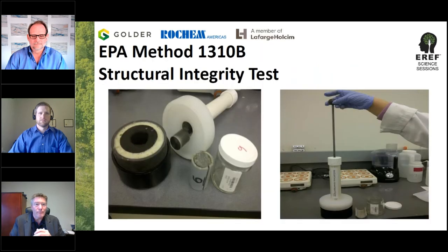And the method that I like the best, and I think the one that is the absolute most relevant, is EPA method 1310B. It's called the structural integrity test. You make these little monoliths. If you'll see in the left picture, there's a number 6, and there's a mold of a prescribed size, 7.1 centimeters tall, 3.3 centimeters across. You make your mix. That's that little vial that you see there, or that mold, that used to be liquid concentrate. It has been blended with the cement binders that I had prescribed for this particular site. And it is put into this mold, and it's by the method, it cures for 30 days.